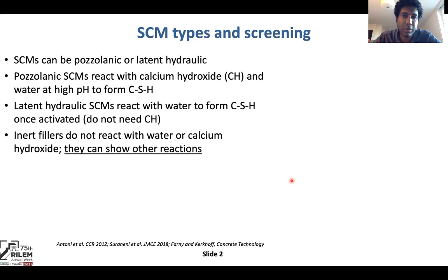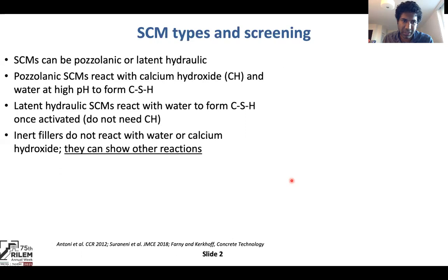Fly ash, for example, is a pozzolanic material which reacts with calcium hydroxide and water at high pH to form C-S-H. Slag is a latent hydraulic SCM — it still reacts with water, but it doesn't need the calcium hydroxide; it'll react with water once activated to form C-S-H. Inert fillers don't show pozzolanic or latent hydraulic reactions, but limestone shows other reactions, such as reactions with carboaluminate phases.